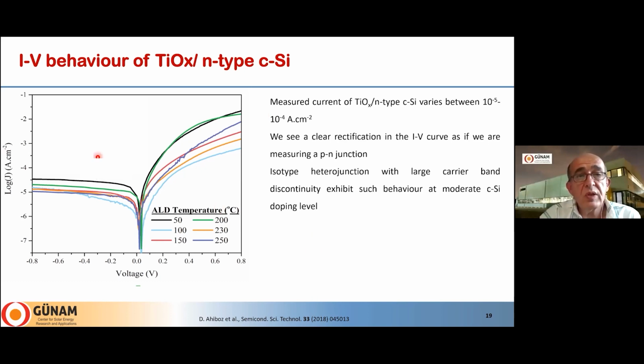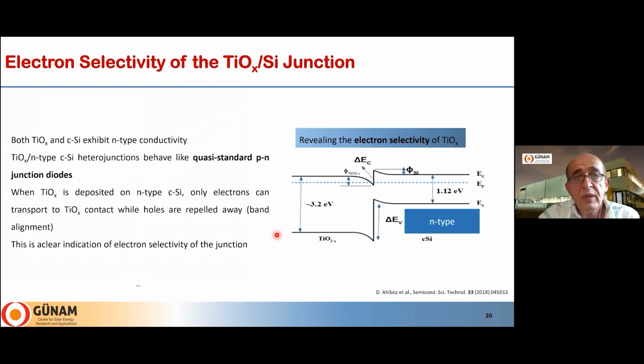It's a good indication that titanium oxide is, when we look at this band diagram, here titanium oxide is here, silicon is here. Electrons can move through the junction very easily because we have a small barrier and a small quantum well here, so it doesn't form a strong resistance against the current flow. However, we have a large barrier in the valence band so that the holes cannot move very easily from one side to the other. These measurements have proven that titanium oxide is a good electron selective layer.